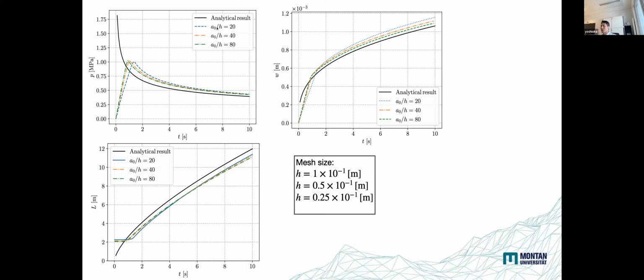So this blue dash case is where we represent the initial fracture with 20 elements, and then we refine the element and so on. As we refine the element, we can represent the analytical solution better. But okay, it's not a perfect match, and this is due to the finite reservoir permeability actually. In the KGD solution, the permeability of the reservoir is 0, but we could not really assign zero permeability because of the numerical difficulty. That's the reason for the slight discrepancy between the analytical model and our simulation result.